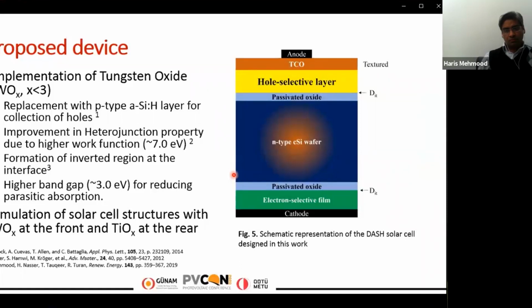The basic purpose of implementing tungsten oxide is that it tends to replace the p-type amorphous silicon because of its high work function of around 7 electron volt. The advantage of employing a high work function is that it induces the inversion of the crystalline silicon surface on both sides. Similarly, the higher band gap of 3 electron volt will reduce the parasitic absorption, and the electron selective film of titanium dioxide will have a low work function.